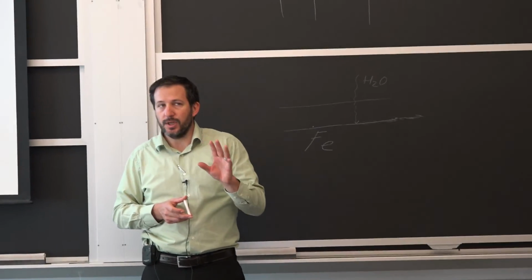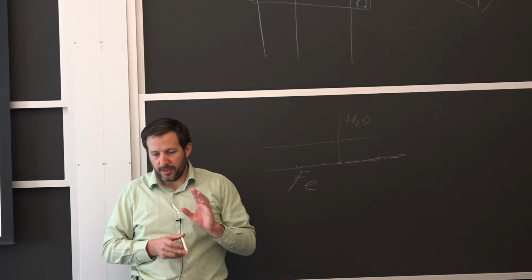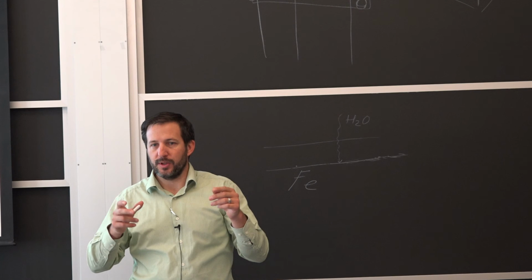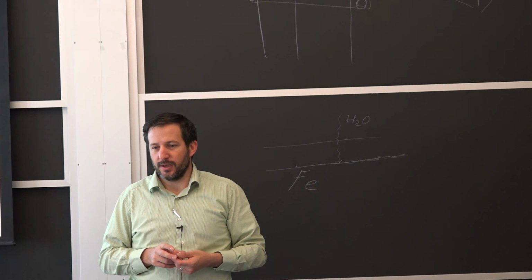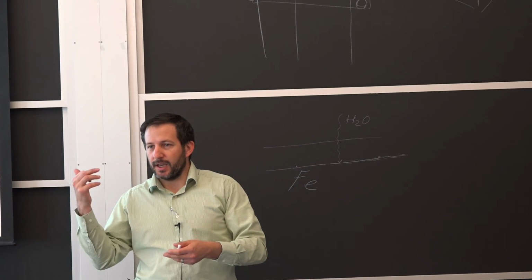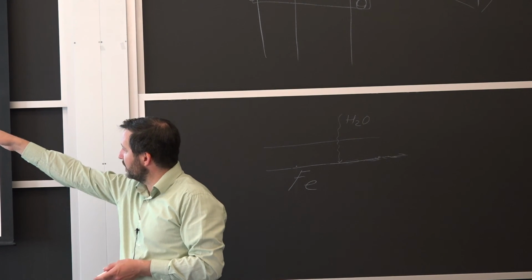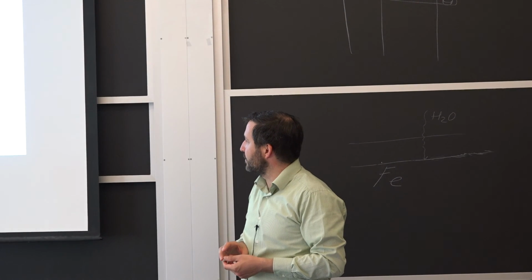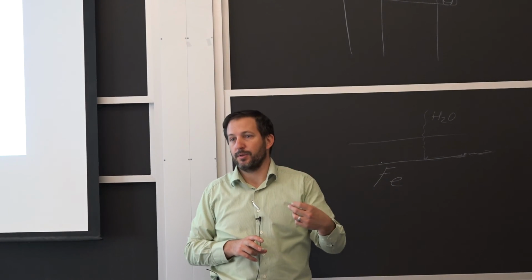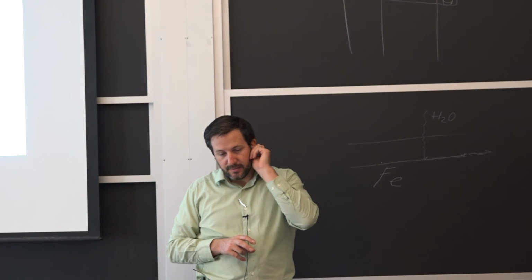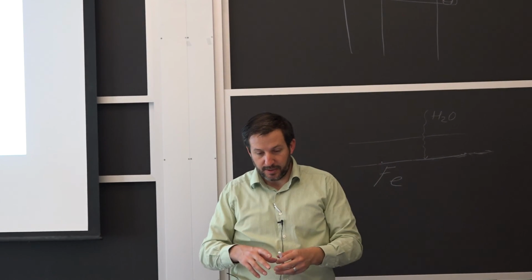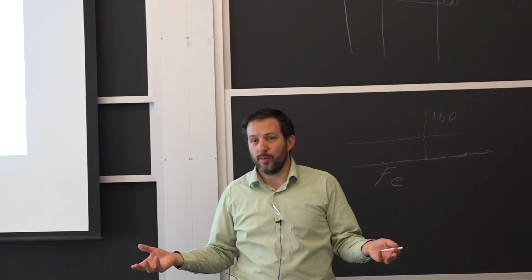One thing to think about when we talk about galvanic couples and you try to assemble something is the smallest piece is what you always want to be the more noble material. So it's not a good idea to use steel bolts to connect these pieces of copper, and that's not a mistake they made. They were using copper rivets, even if they don't have the same strength, they don't have the same characteristics, because you don't want that small element to be the one that's corroding the most. So the ideal scenario here would be this wrought iron armature being, in surface, a lot bigger than the copper surface, but it's not the case.